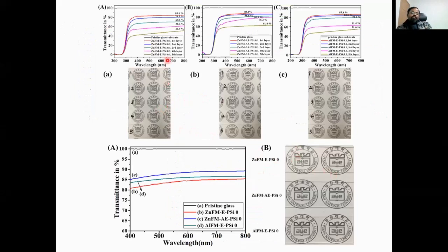We also compared this coated substrate with different layers of this hydrophilic coating on the hydrophobic substrate. So we tried almost five layers of hydrophilic coating on this substrate. It shows that while increasing the layer-by-layer thickness on the substrate, the transparency is reduced. So we just kept one layer coating for our further application, because one layer is enough to make it highly transparent. And without silica it also shows similar results, around 80 to 85% transparency.